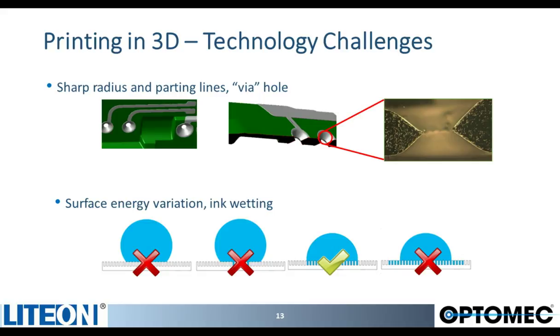The cone shape of the via creates a very sharp edge midway through the part. Tooling mismatch can make the step even bigger, and in mass production over time, the parting line in the tooling can grow, creating a barrier for the ink.